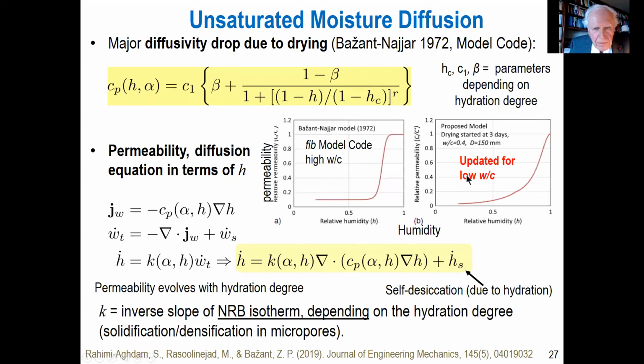All right. So now we must calculate diffusion. We must calculate diffusion in the cement shells, but mainly for fitting data, we must calculate diffusion for the whole specimen. I will not spend much time on this, although it is a big subject, but it's a highly nonlinear phenomenon that was found at Northwestern in 1972. At that time we got the data from PCA on humidity distributions and evolutions by the newly developed humidity gauge of Monfore and Copeland. We came up with this formula, which is plotted here. Diffusivity or permeability both decrease from 100% here down at a 50% humidity. At that time, we believed it's about 20 times smaller, and the formula gives exactly that. And this is a guess down.